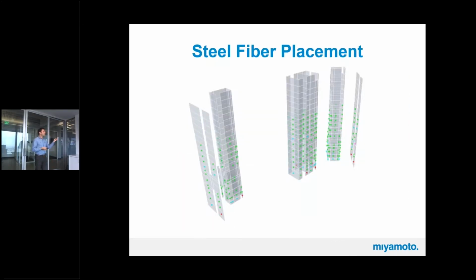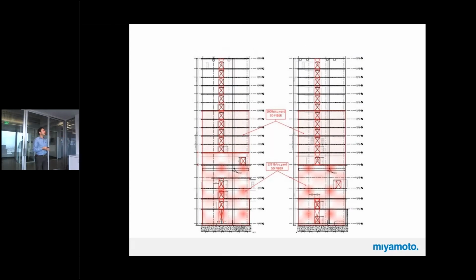So having this information, we didn't want to specify the same amount of fiber everywhere, okay? Because we wanted to specify a higher dosage in places that experience higher damage. For example, these are the wing walls that were important for us, and we specified a higher dosage of the fibers for the first 3 floors and a lower dosage of fiber for upper floors.